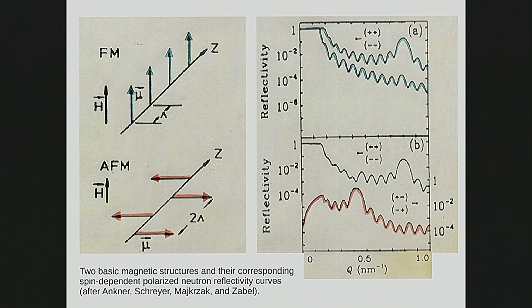So now you get a big magnetic scattering peak that occurs because of the reciprocal relationship between real and scattering space. It represents the magnetic scattering, and it's all spin flip scattering that occurs at half the Q value of the nuclear scattering peak that occurs at this periodicity. Okay? So again, yes?